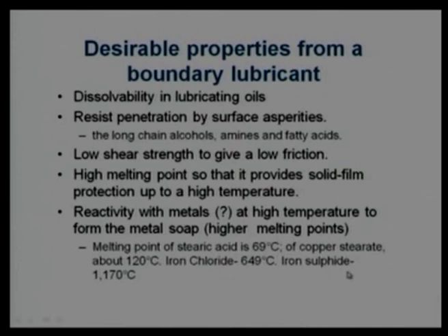However, if you want to go further on the higher side, then sulfur should act. We say the iron sulfide, which will melt at 1170 degrees centigrade, gives a very high temperature. They can be used as high temperature additives. They are giving good results at high temperature.